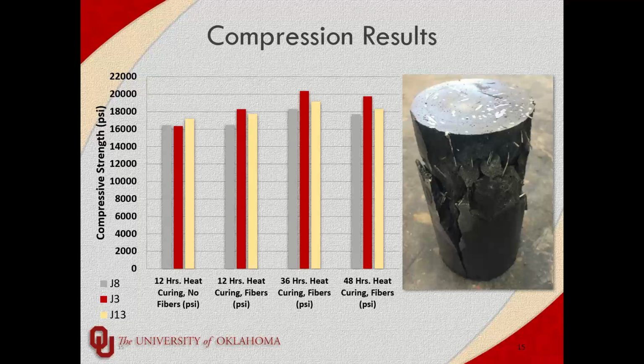As I mentioned, the compressive strength was tested at different heat curing times. The temperature was the same, and they all had about the same amount of water in those little tubs. One thing we noticed was that 36 hours was about the best heat curing time for all three concretes that we tested.